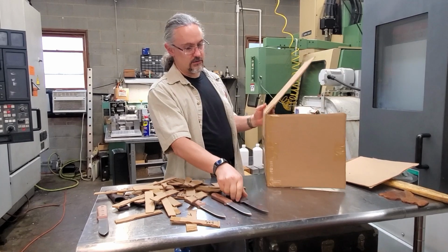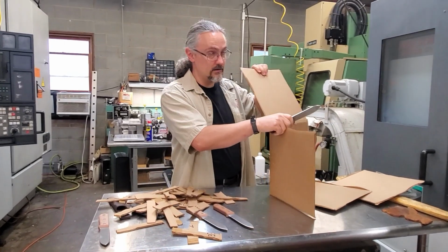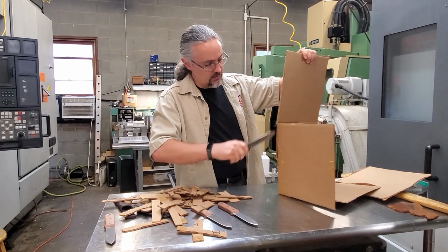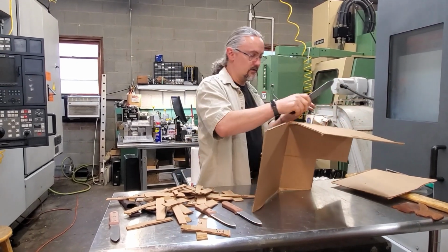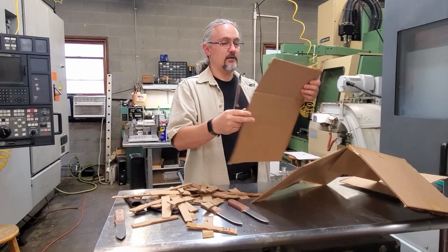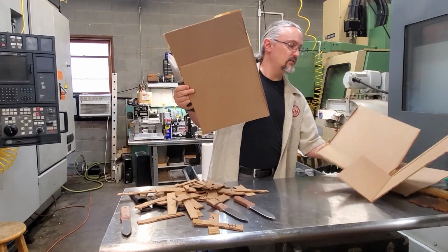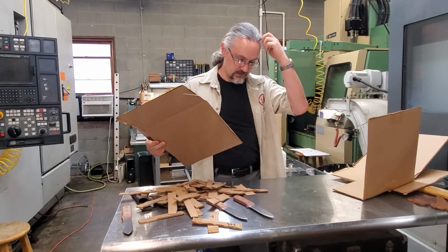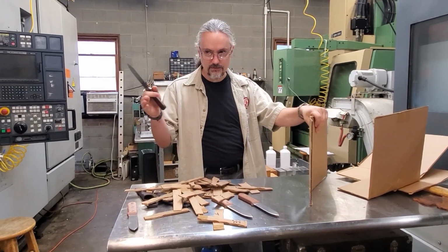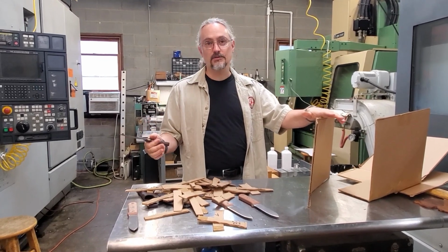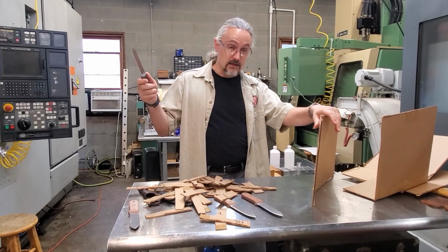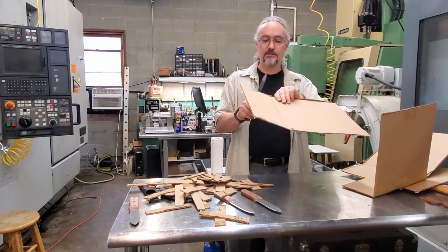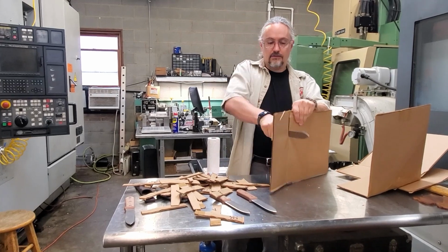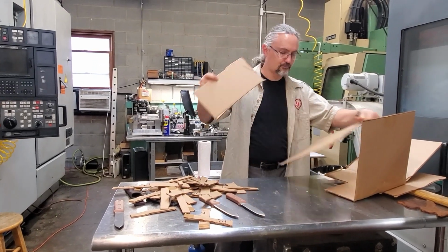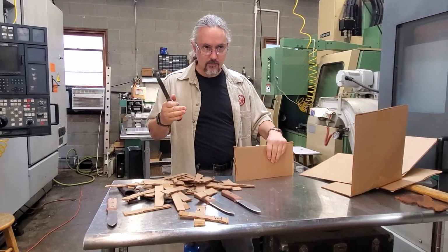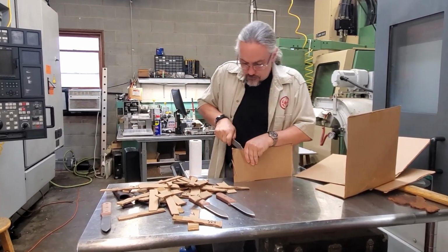So when you're doing a secondary hardening hump, or you're doing a low temp tweak, you want to make sure that your quench rate is fast enough, and you also want to make sure that you're quenching to martensite finish, which is kind of an arbitrary number. There's not really a martensite finish. You're never going to get 100% martensite, but there's a good rule of thumb that if you can get below 100 degrees Fahrenheit, and do it without temperature reversals, you're going to be able to get your best martensite conversion.